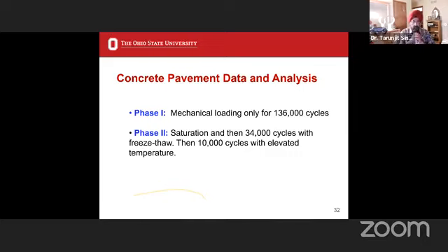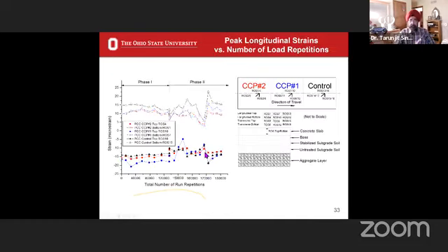The second part of the data is dealing with concrete pavements. In this case, again, we had 136,000 cycles, and then we had saturation and freeze-thaw for about 34,000 and 10,000 with elevated temperature cycling. Similarly, we have several types of monitoring that we did, into the peak longitudinal strains. They were similar between asphalt and concrete, between CCP and the control section.